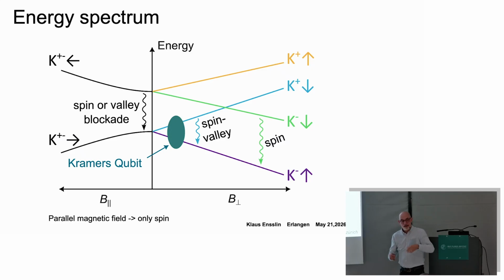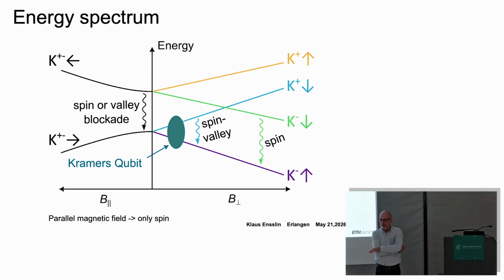And there have been all kinds of numbers in the literature, but meanwhile, there are different experiments with different groups that basically tell you that the spin-orbit interaction is 75 microelectron volts for graphene. For bare graphene, bilayer graphene, 70 to 80 microelectron volts. So that sounds like a small energy scale, but it's a significant energy scale if you work at 10 millikelvin electron temperature. So basically, this is much larger than kT.